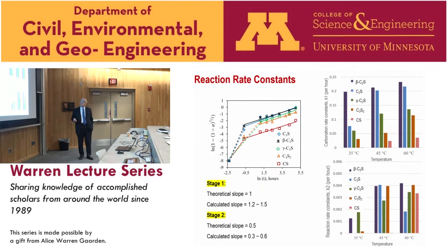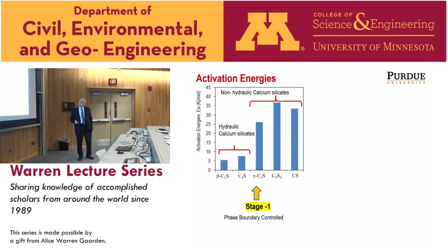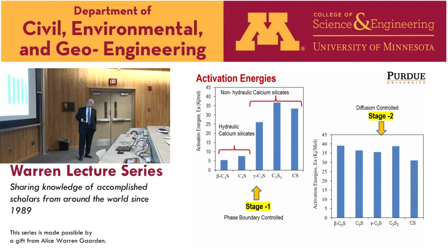So based on all this, we determined the rate constants, and you can see that they were different for different materials. We've done some modeling, and theoretical slope that we were expecting for the stage 1 should be 1. We got somewhere between 1.2, 1.5. And theoretical slope for the second phase should be about 0.5. We got anywhere from 0.3 to 0.6. We also got the activation energies associated with the process. And you need those values for both stages if you want to develop a model for optimization of the carbonation process. How much CO2, what concentration, what temperature. You cannot move forward if you don't have this data. That data was not available for the materials that we were interested, so we determined those for all those materials that are part of this cement.